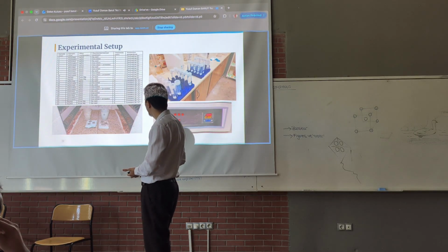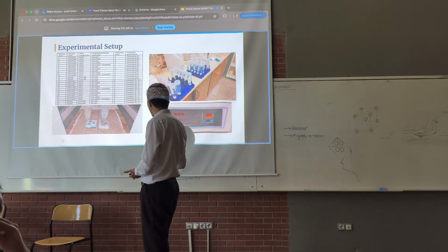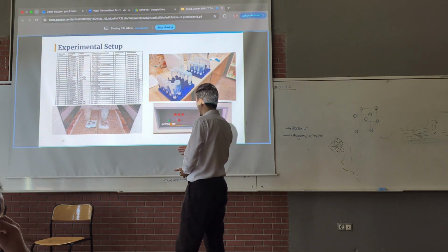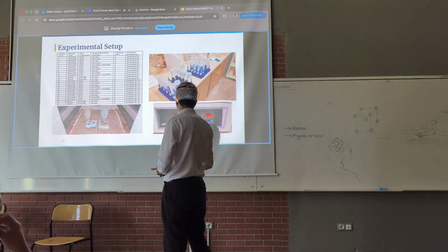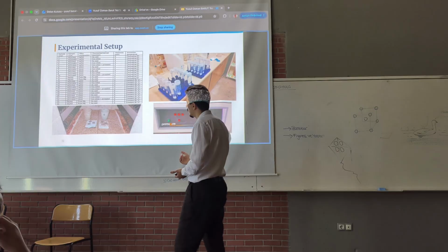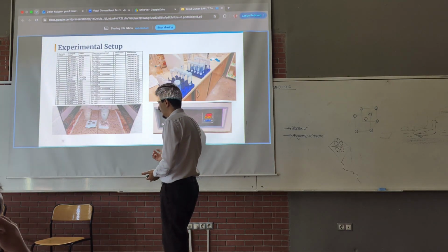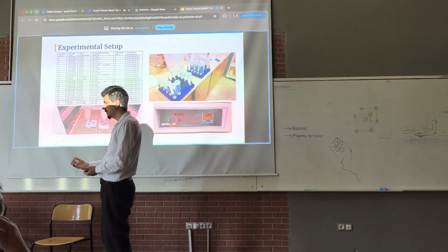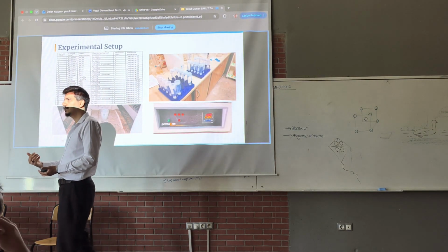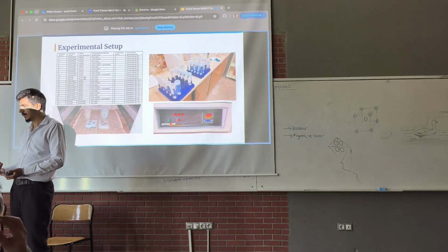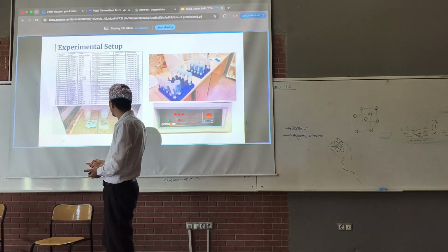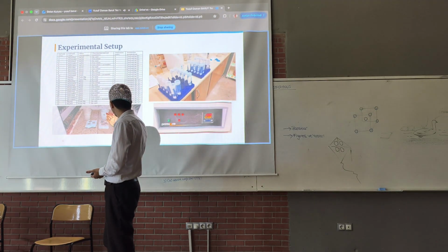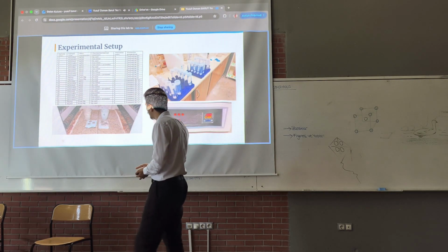So in order to acquire this annealing, we subjected some of our magnesium alloy plates to 400 degrees Celsius for about an hour, and in order to have a high concentration of ammonium dihydrogen phosphate and magnesium solution, we increased the temperature to 35 degrees Celsius.